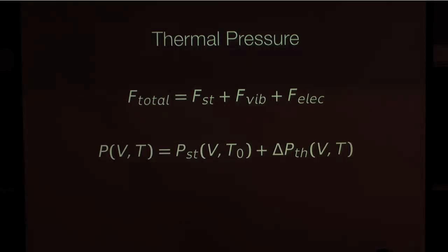Yes, that's a good point. I'm actually deriving all these equations under the assumption of harmonic oscillation behavior, which I haven't described yet, because I'm not getting into the thermal part yet. Because if the potential for the interaction of atoms is perfectly harmonic, then you would not have the Grüneisen parameter. The Grüneisen parameter is an outcome of the anharmonicity of the potential. Yep, that's true. So you cannot derive, say, thermal expansion if you don't have anharmonicity.